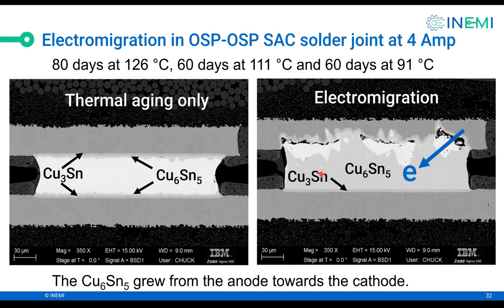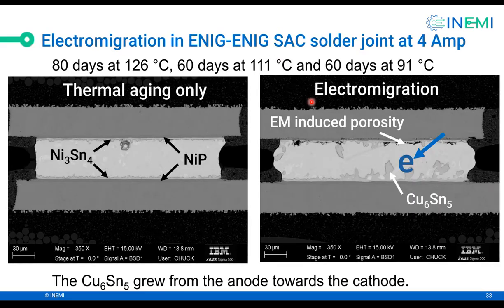So this is OSP. ENIG is a different story. Here, the nickel is a good diffusion barrier, but I'll show you we do have cracks in the nickel. Copper does get through. So all this Cu6Sn5 you see, that's because of copper coming from the top copper termination, metallization. Because I'll show you this porosity in the nickel plating.